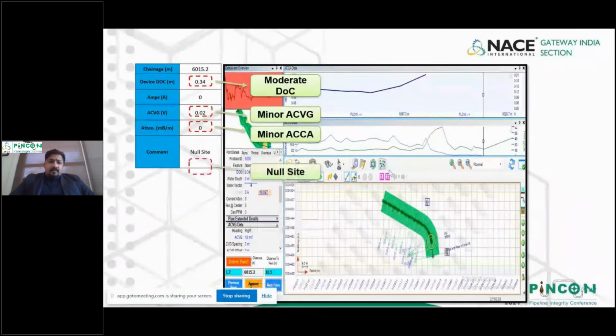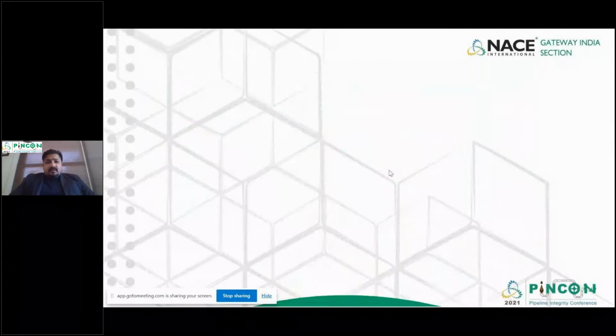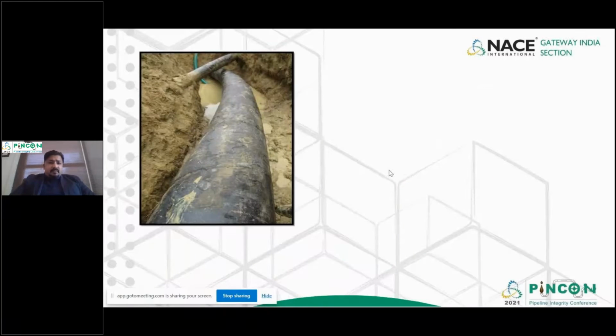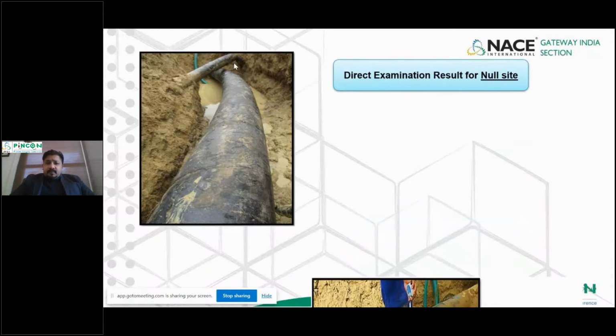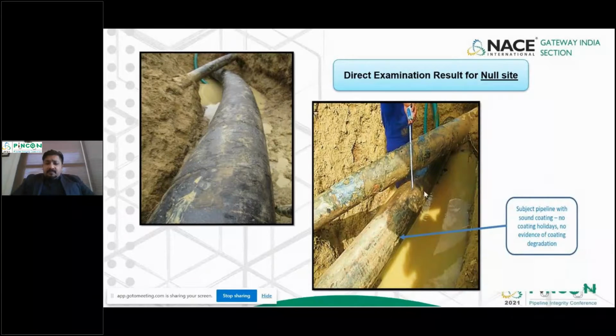This was in particular a null site, and after excavation, that is what we find. We find perfect coating in the area. There was one pipeline crossing on top of it, and we see that the subject pipeline which was being surveyed did not have any coating anomalies, nor does it have any problems. Although the pipeline on top, the one which is crossing, had a couple of coating holidays, and most probably the ACVG minor indication that we got in this location could have come from this pipeline, which is crossing over our subject pipeline in this particular case.